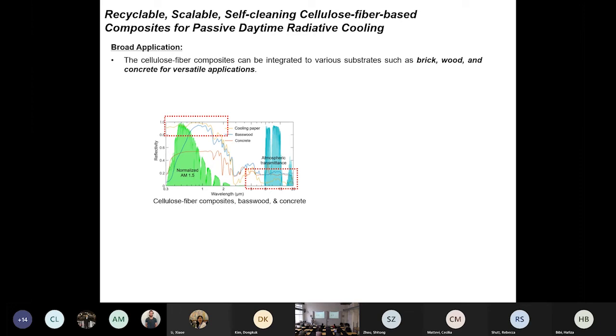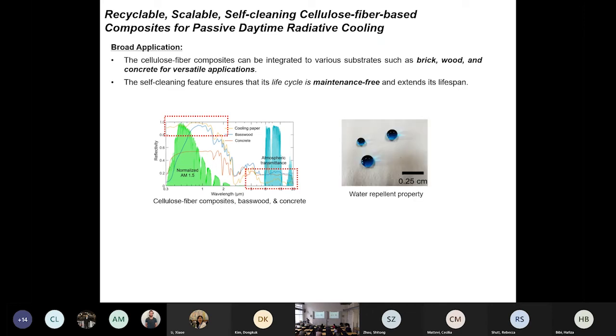And we already demonstrated experimentally that the cooling paper performed really well with integration to the concrete and the basswood. Without cooling paper, you can see the red curve for concrete and the blue curve for the basswood. These are 2 materials that we commonly use for building materials. And with the cooling paper, clearly the reflectance is pretty high over the visible light range and the near infrared light range, and also with a really high emittance. That means with really low reflectance in the first window of atmospheric transmitted window between 8 and 13 micrometers. That's the concept. So we demonstrated the self-cleaning feature, and it's going to extend the life cycle of the material.